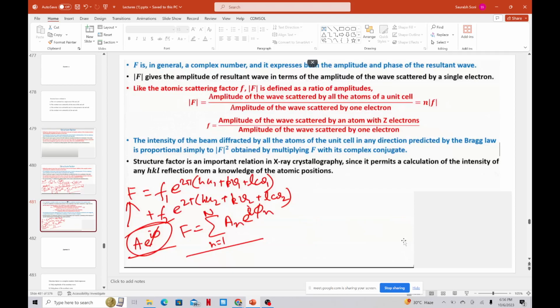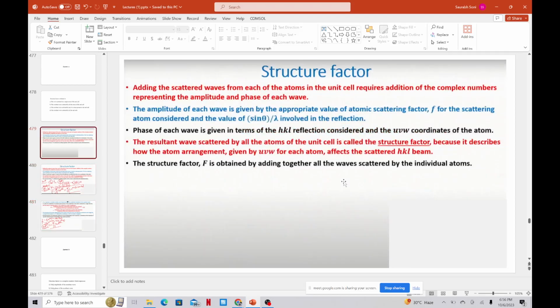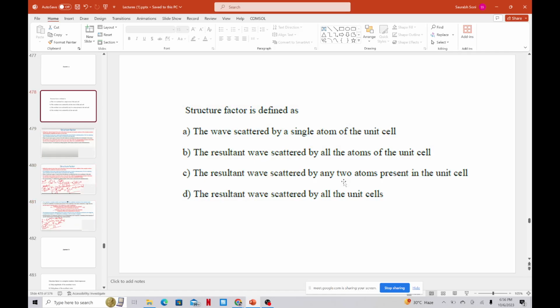The intensity of the beam diffracted by all the atoms of the unit cell in any direction predicted by Bragg's law is proportional simply to |F| squared, and this is obtained by multiplying F with its complex conjugate. So here this is your F, and when you multiply this you will get this. So the formula of F, in this way, you will get summation of n equals 1 to N, f e to the power i phi n. The structure factor is an important relation in X-ray crystallography since it permits a calculation of the intensity of any hkl reflection from a knowledge of the atomic positions. So it is nothing but the resultant wave scattered by all the atoms of the unit cell.